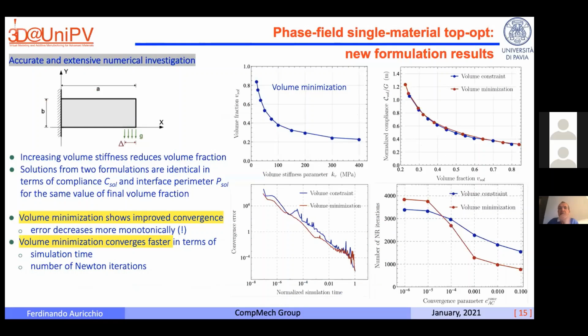And the nice thing is that you can run your simulation and you can show that the volume constraint and volume minimization approaches obtain, you see the two curves are identical, which means that with the two formulations you can obtain basically the same results, with the difference that in volume minimization you automatically in some sense also minimize the material you put in your formulations.